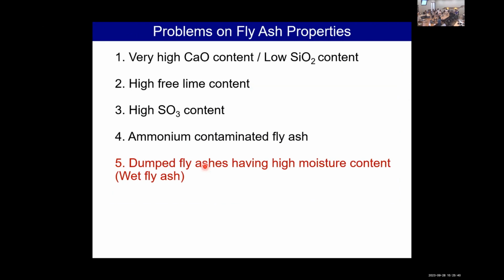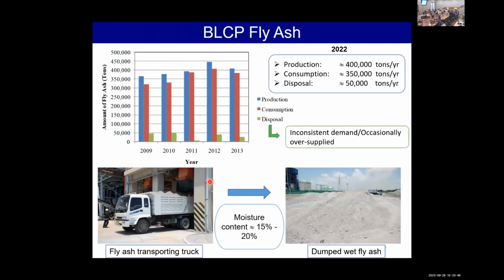Okay, for the last one, the problem about damp fly ash, having high moisture content, or wet fly ash. This is the BLCP fly ash data. We can see that there is some disposed fly ash that has to be dumped inside the power plant. This comes from the problem of inconsistent demand and occasional oversupply. Therefore, the fly ash is sprayed with water to get moisture content above 15% to 20% and dumped.